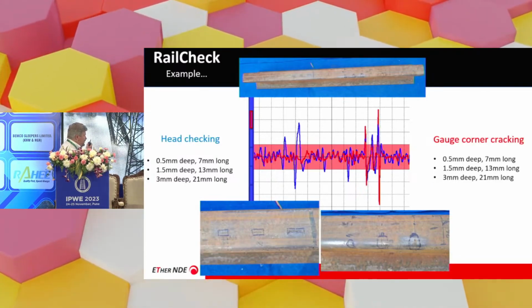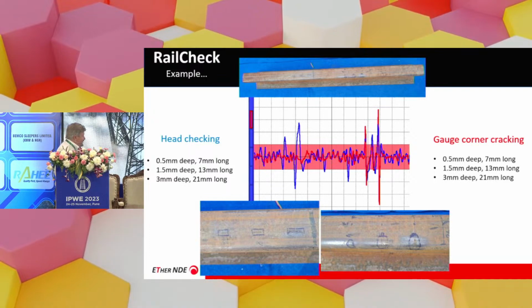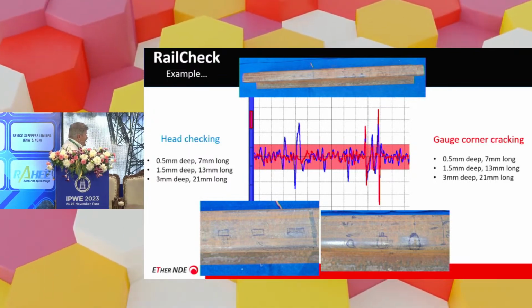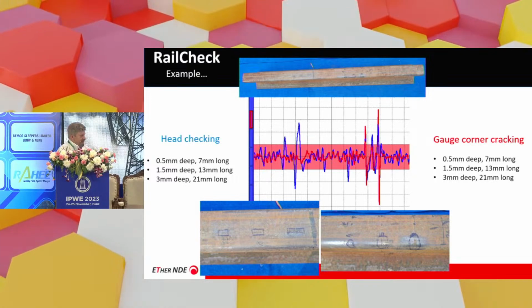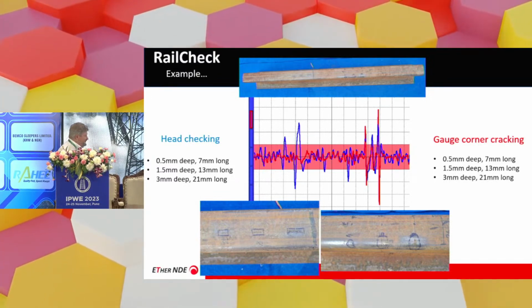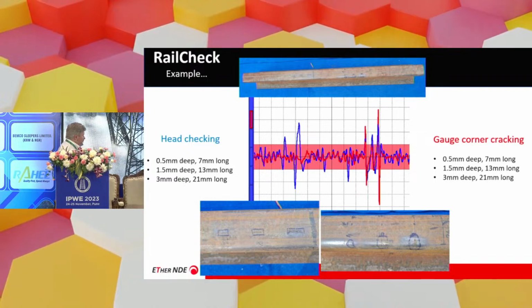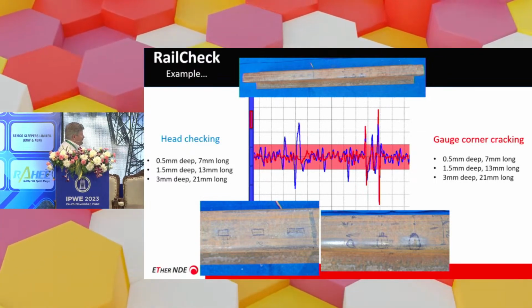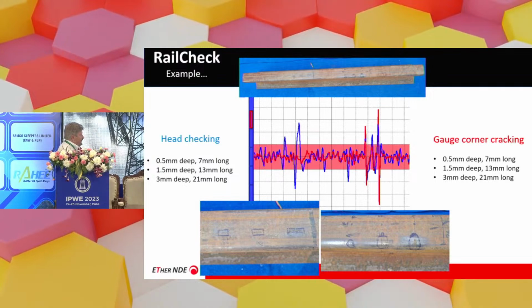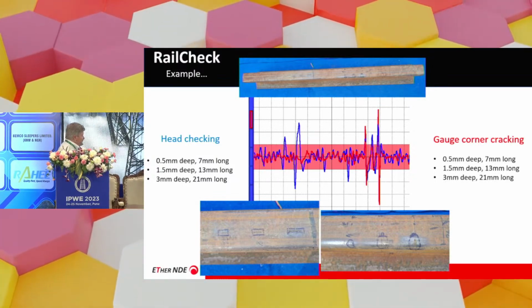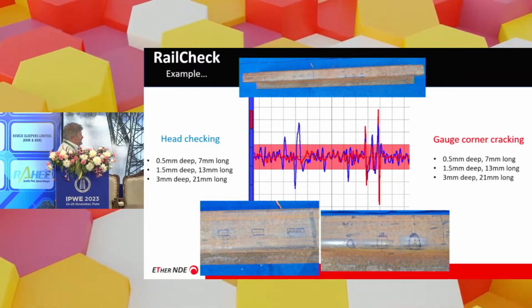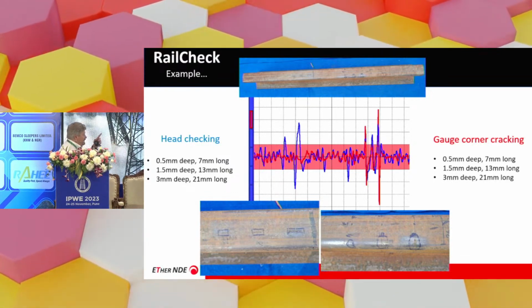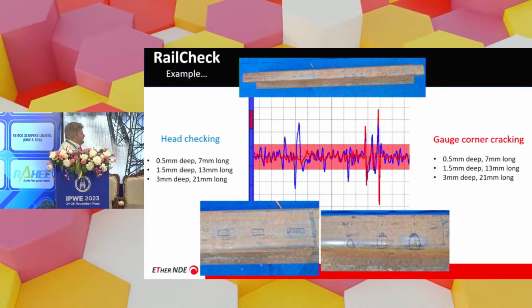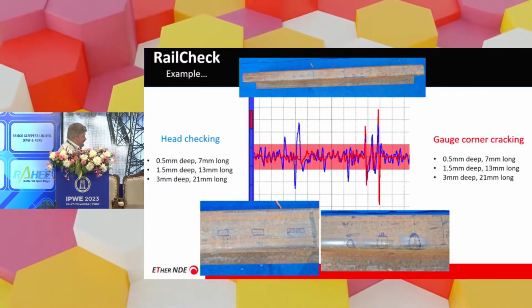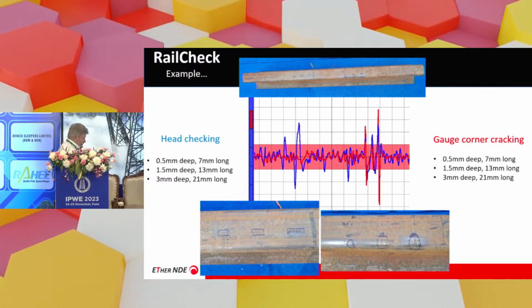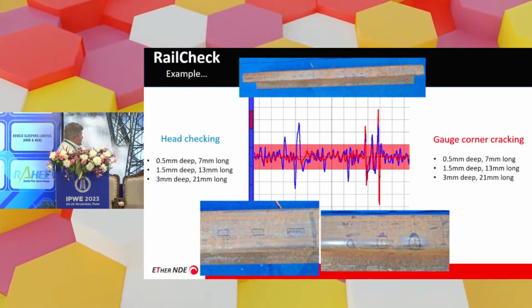If you come to stand 18, you can see this in real time. Modsonic made us some notches in some Indian rail, some longitudinal notches, which follow this basic formula: 0.5 millimeter deep, 1.5 millimeter deep, 3 millimeters deep, and then different lengths to simulate defects. As you appreciate, these are quite shallow defects in the railhead. Then gauge corner ones follow the same pattern, but it's slightly trickier because you're going around a curve. Up here are the responses from these defects.